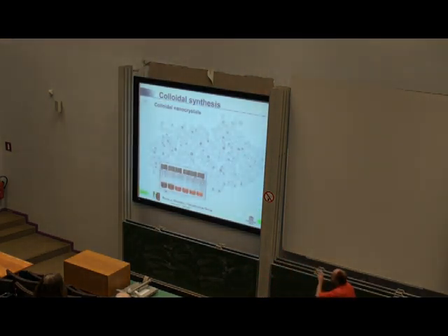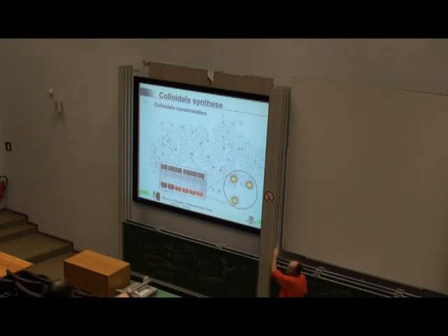So we have these vials. It's liquid, it's solutions. Typical solvents are toluene, chloroform, apolar stuff. And in there, if we could zoom, if we could magnify that, we have all these tiny nanocrystals. And I plot them as a kind of yellow circle, let's say a yellow dot. And then we have these little molecules around that. And that's the surfactant. The idea of the surfactants is that they adsorb on the surface of this nanocrystal. And they are there to prevent all these particles from aggregating. We want separate nanocrystals. We don't just want one big chunk of material. We want separate particles. And that's the role of these surfactants.